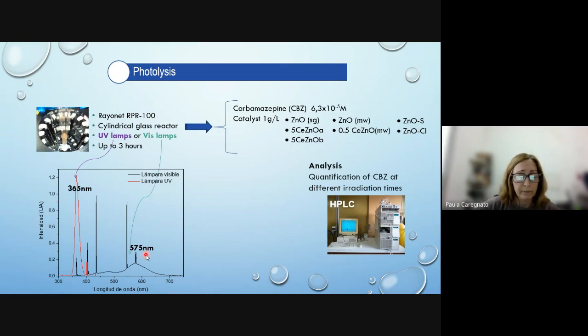Here I show you the spectral irradiance of the UV lamps. It is the red line. We can see that it has an emission maximum at 365 nanometers, and the emission spectrum of the visible lamp presents several peaks with a maximum at 575 nanometers. The quantification of carbamazepine at the different irradiation times was performed with HPLC equipment with absorbance detection.